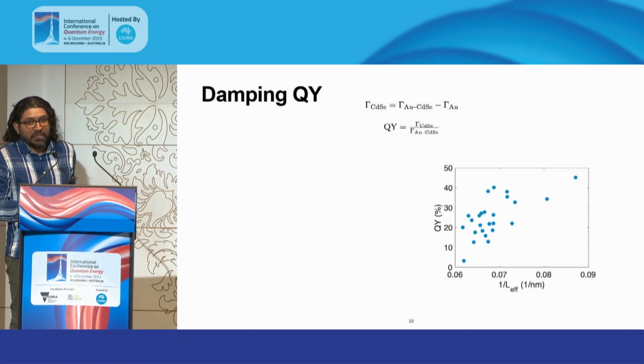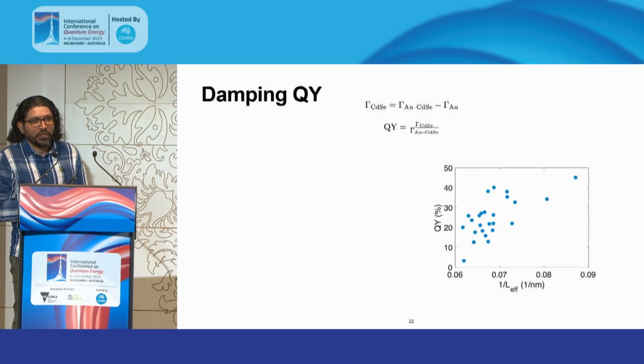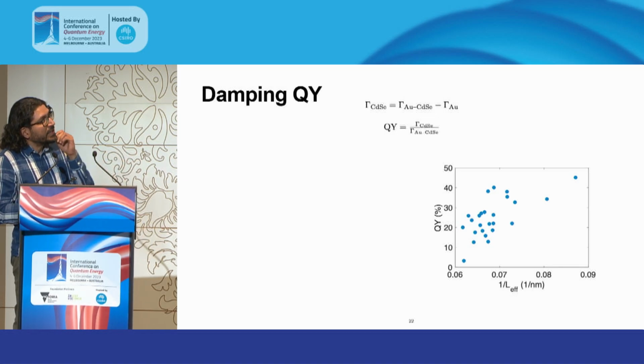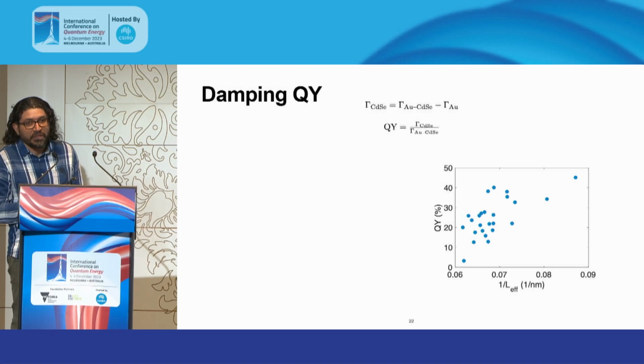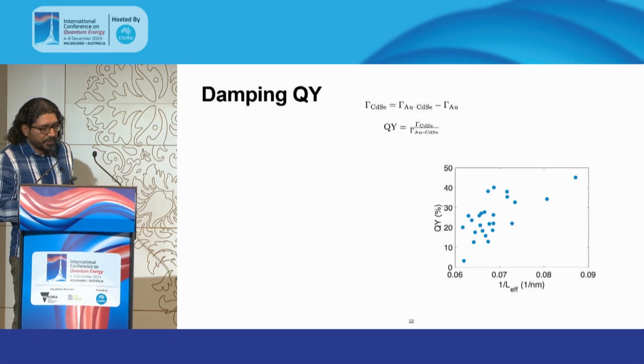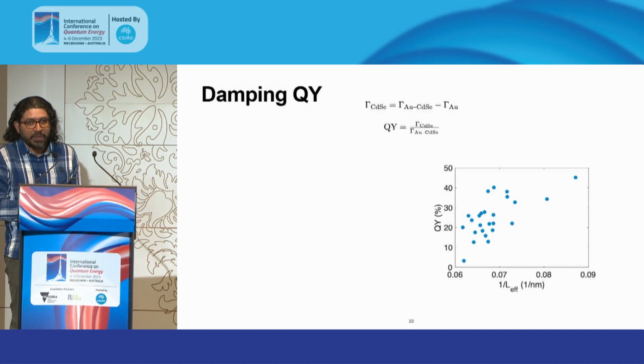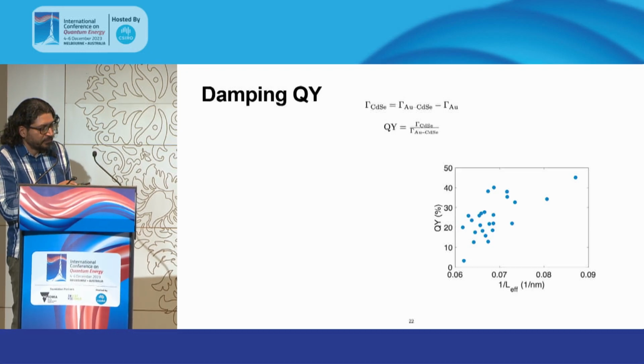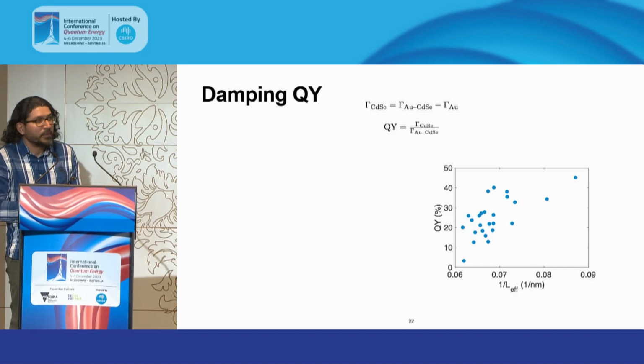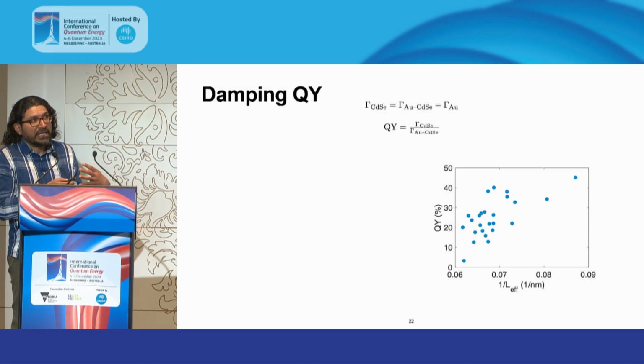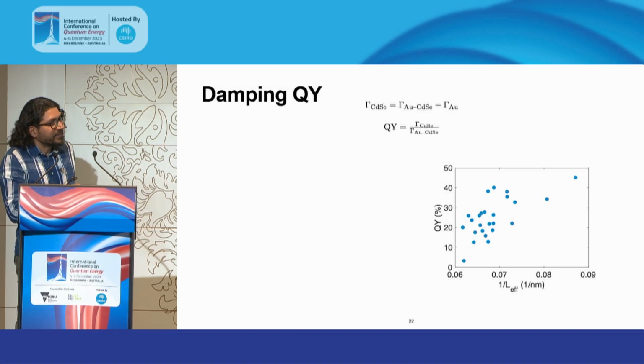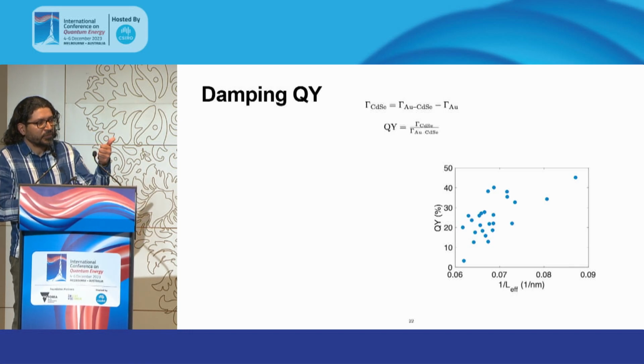This allows us to compare our data to the data by Professor Tianquan Lian. Remember, he reported a 24% yield. That was a groundbreaking Science paper. We are now reporting that with some of our particles, we get at least double the efficiency, up to almost 50%, which is quite encouraging, in particular because our data allows us to identify what happens in this data point in terms of composition, geometry, and quality of the metal to semiconductor interface.